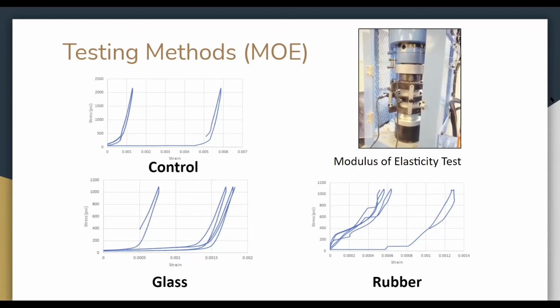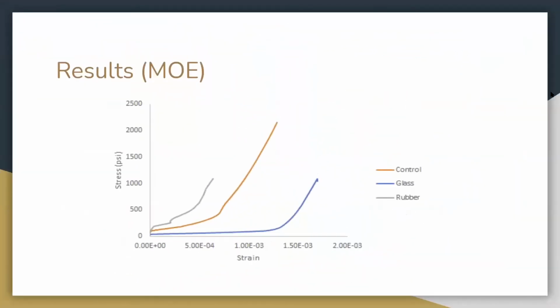After analyzing all the data and adding them all in one plot for comparison, we ended up with a graph like the one shown here. We can see the stress-strain curve for the control, rubber and glass samples. We can calculate the modulus of elasticity by calculating the slope of the straight line in each sample. These lines are easily identifiable for the control and glass samples. However, for the rubber sample, the modulus of elasticity was calculated using the average of many calculations in order to have more accurate data due to the nature of the stress-strain curve of the rubber sample.